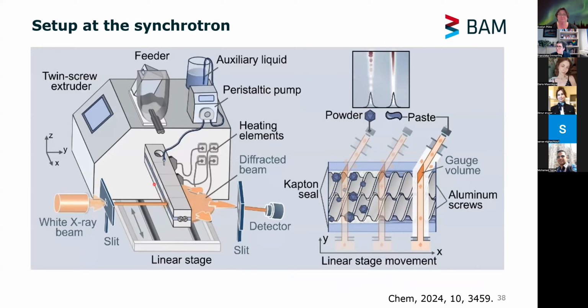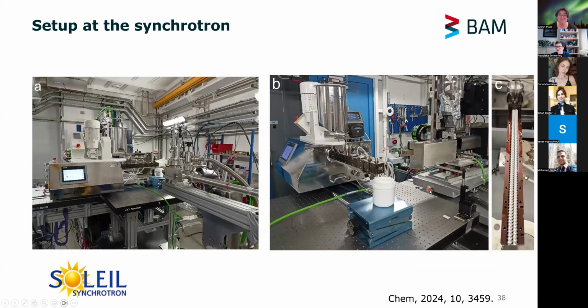A bit of adaptation is still necessary. You can see that here, that is our extruder. You see the barrel here. We had to have a linear stage to address different positions, and we also had to exchange these steel screws by aluminum screws, so that there is a better chance to really shine through, and then we can easily monitor these types of processes at different positions.